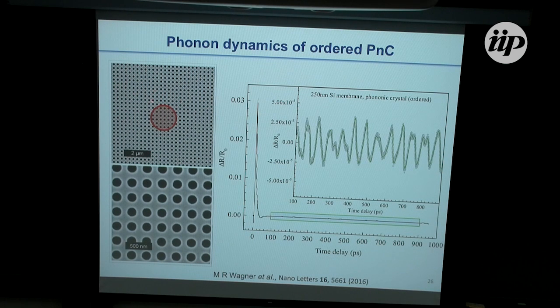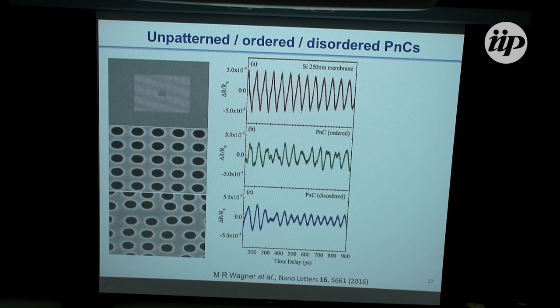So the pump laser and probe laser are placed in some area of the phononic crystal. And the large picture is that you have a very fast electronic response. As soon as there is a flux of photons impinging on the sample, you have a generation of electronic excitations by a photon-electron interaction, which is very fast. Something in this time scale is just a peak. And then you have a set of oscillations as a function of time, which, when amplified, give you information that you can extract taking the Fourier transform of that peak. And that is what we call the lifetime of our phonons.